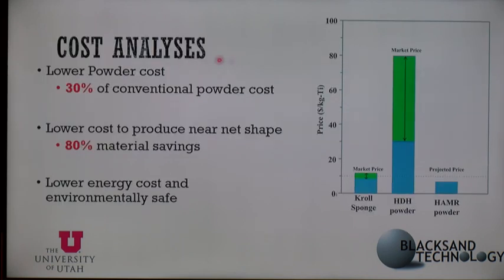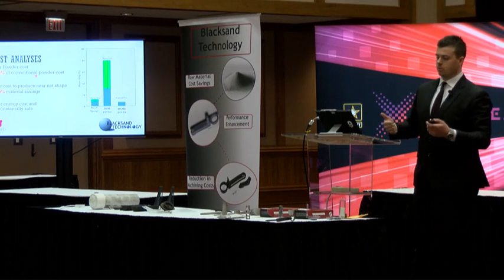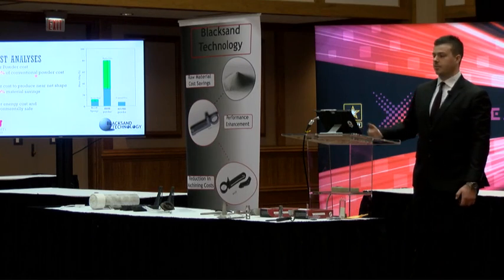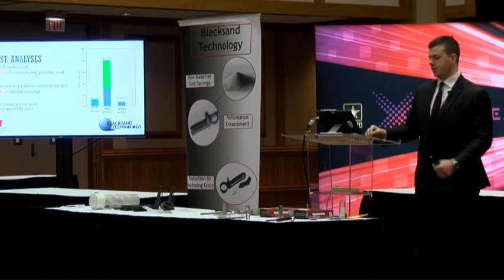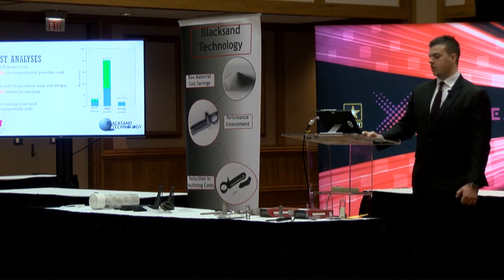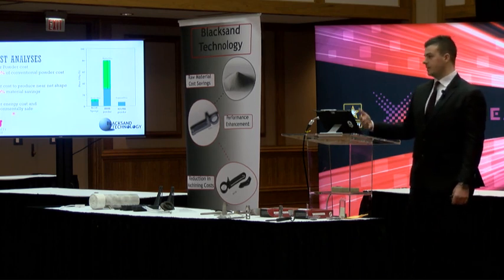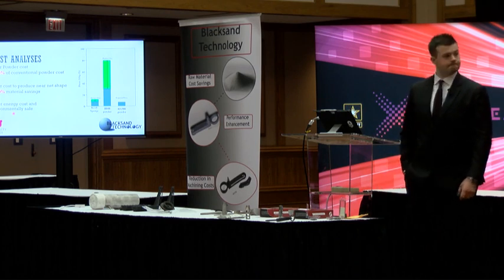As far as cost analysis goes, we have a lower production powder cost, as I already went over, by approximately 30%. And due to having a higher near-net shape, we can reduce our machining costs, with about 80% savings of wasted material. So there's a lower energy cost, and it's environmentally safe due to not having titanium tetrachloride or corrosive materials.